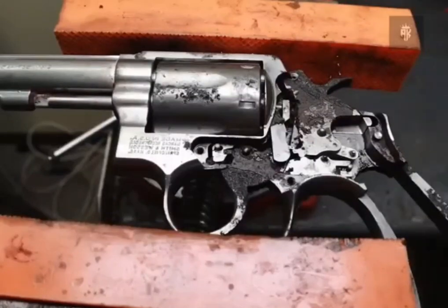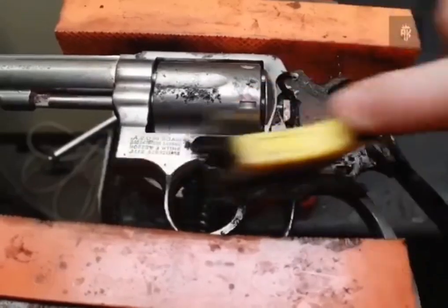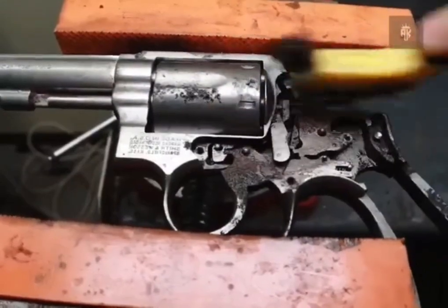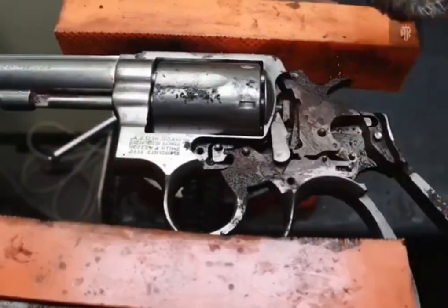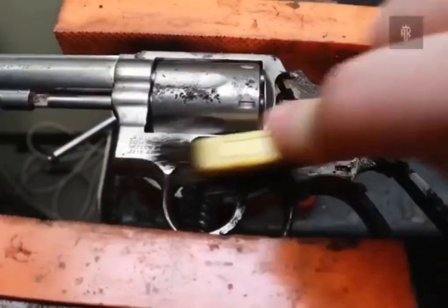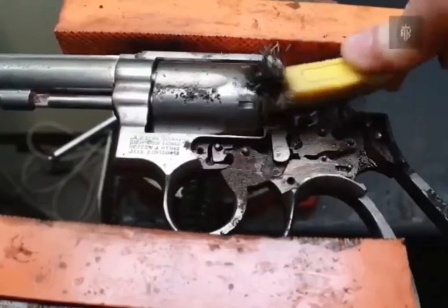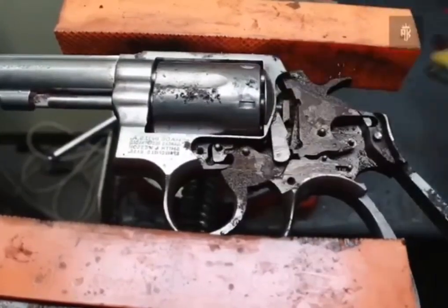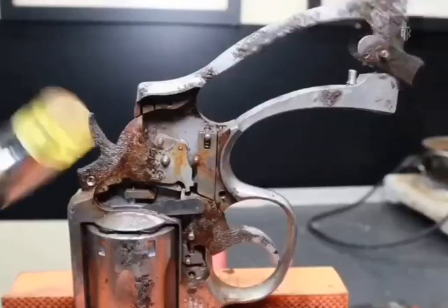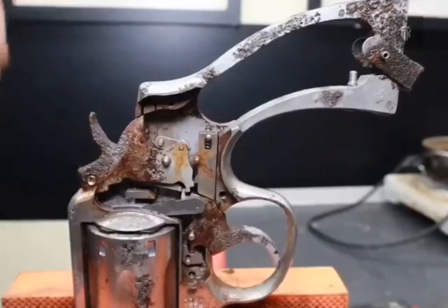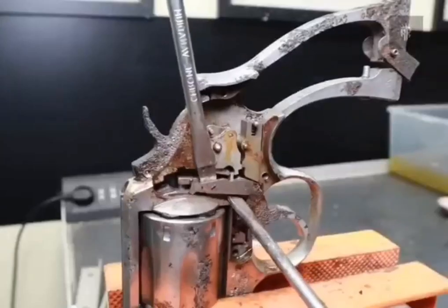Notice how on stainless steel, corrosion takes the form of localized groups of deep pits surrounded by healthy material. On the trigger and hammer, however, the corrosion appears more widespread, and that is usually due to them being made of a slightly less noble alloy than the rest, and through the magic of galvanic corrosion, they get corroded instead of the more noble surrounding material. In any case, having removed the side plate, the hammer is no longer squeezed by the expansion of rust, and I finally managed to get it moving again.